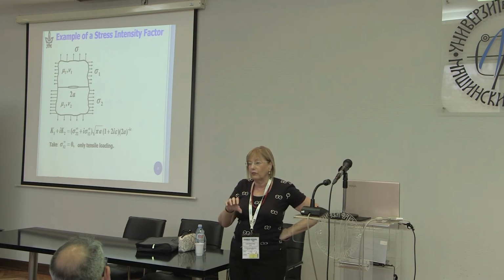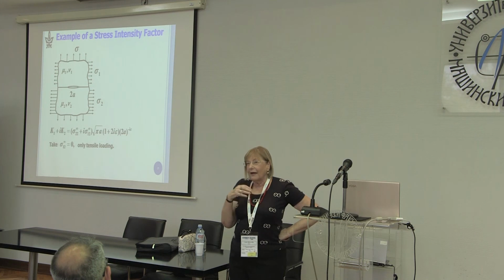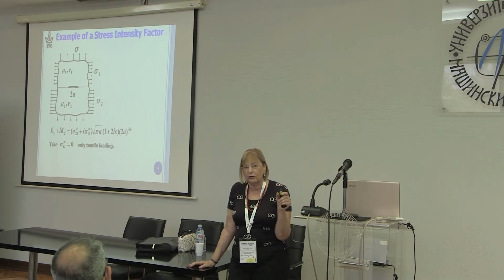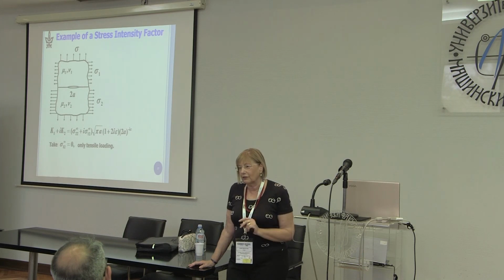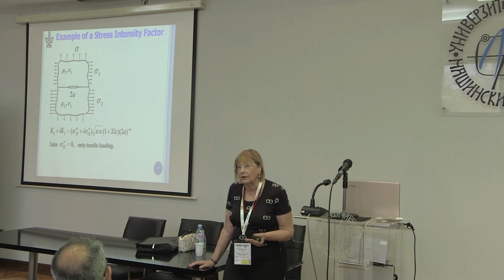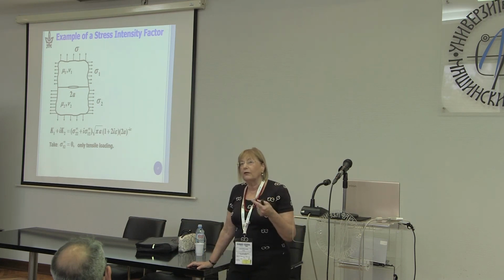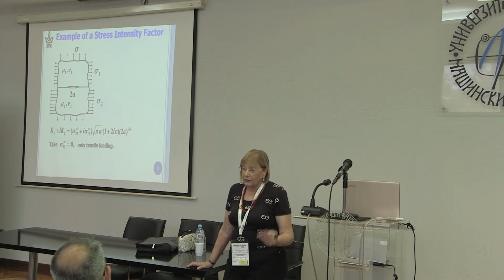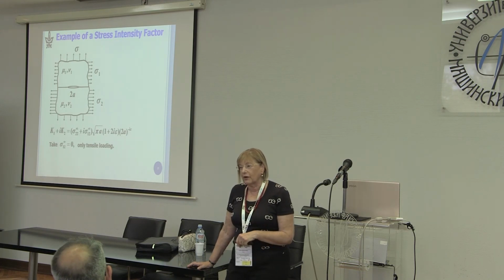But even so, we don't get great results in the 4 elements, or the 2 elements if it's a symmetric problem, adjacent to the crack tip. So we're always going outside that zone. And so unless you have a very large oscillating zone, interpenetration zone, you probably won't be in that zone when you're going outside. So we do go outside. It's really not a problem. You can do the calculation, and we don't just calculate in one ring. We calculate in like 7 rings, and we look at the difference, the path independence, and if it's not sufficiently path independent, we refine the mesh, and we're checking ourselves all the time that we're getting good results.